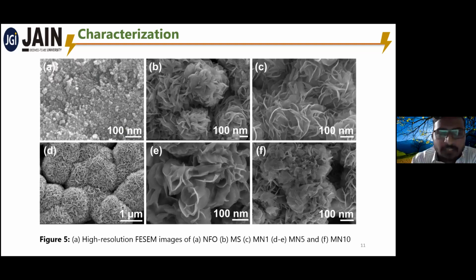Yes, sir. Images D and E represent the 5 mg addition, while image F represents the 10 mg addition. Maybe nickel ferrite is more deposited or anchored on the MoS2 nanoflowers. Due to that, the petals are slightly agglomerated compared to Mn1, pure MoS2 and Mn5. Due to that, different structures are observed.